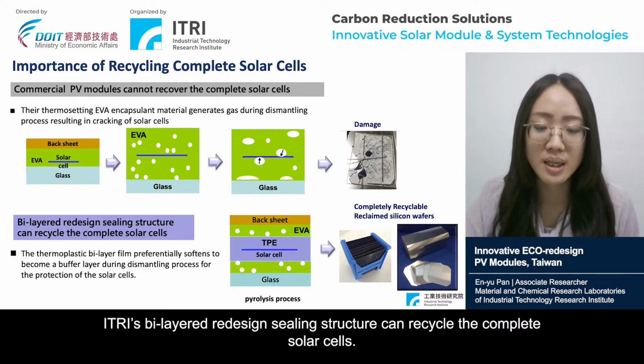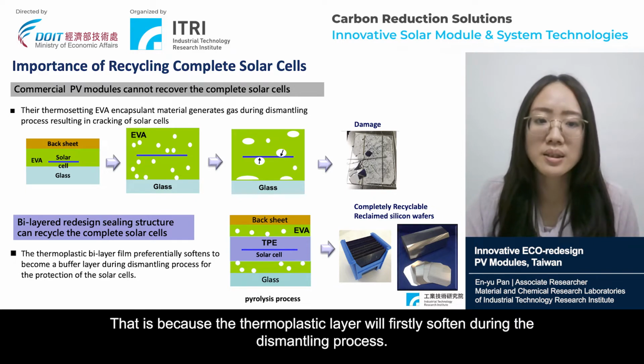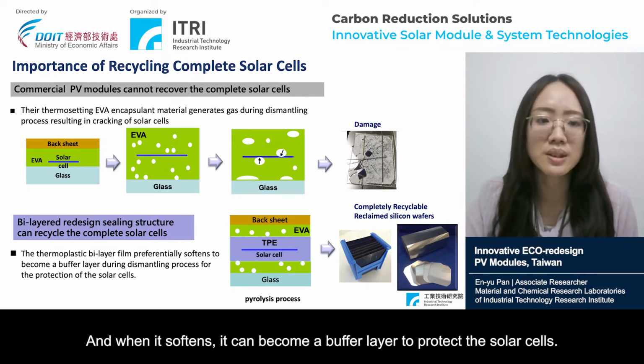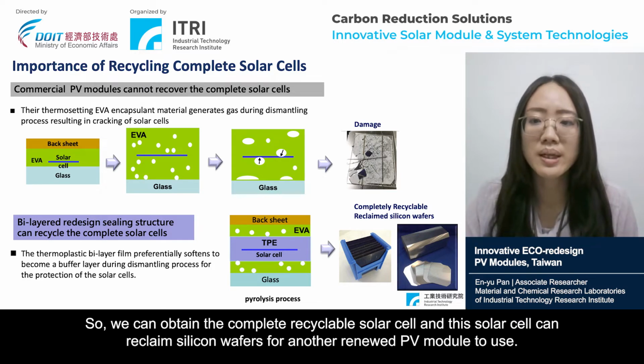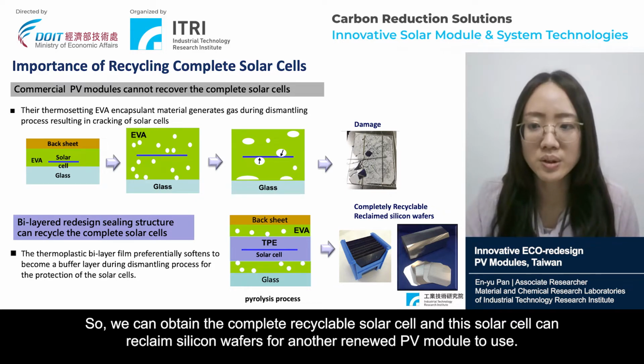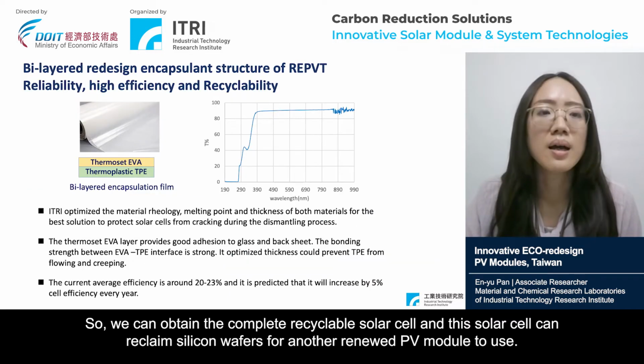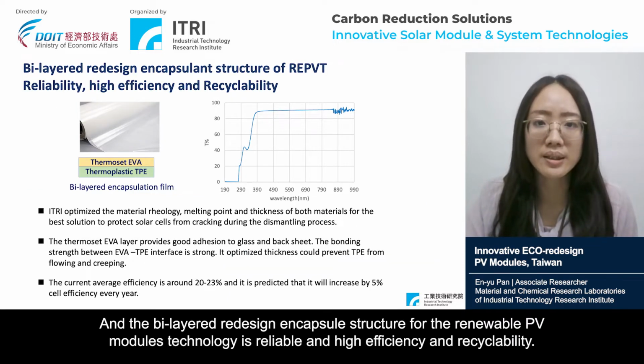Our bilayer redesigned sealing structure can recycle the complete solar cells. This is because the thermoplastic layer firstly softens during the dismantling process, and when it softens, it becomes a buffer layer to protect the solar cells. So we can obtain the complete recyclable solar cell, and this solar cell can reclaim the silicon wafer for use in other renewed PV modules.